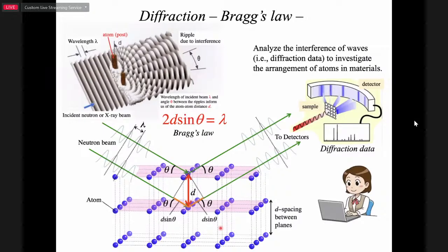This picture shows the arrangement of atoms in material. As you can see, the neutron beam is scattered by each atom. So please note that the neutron wavelength is the same as the distance between atoms here and here. If Bragg's law, 2d sin theta equals lambda, is satisfied, you can detect neutrons on the detector like this as diffraction data. So collecting the diffraction data, and if you succeed in analyzing it, you can get information about the arrangement of atoms in the materials.